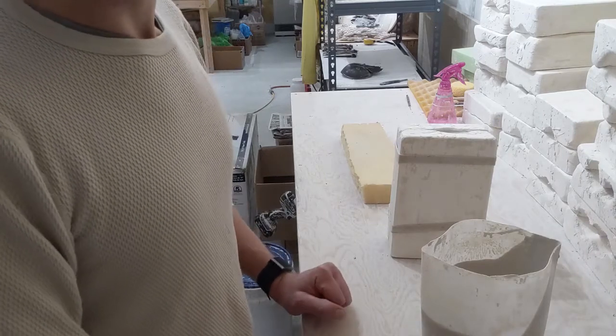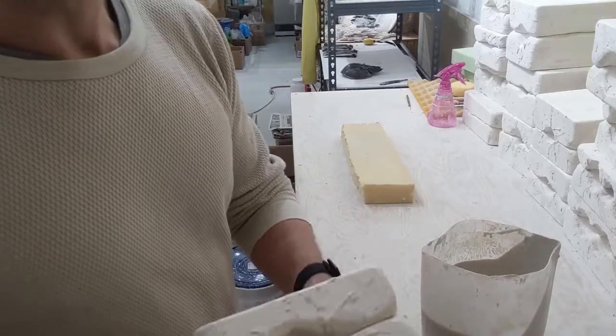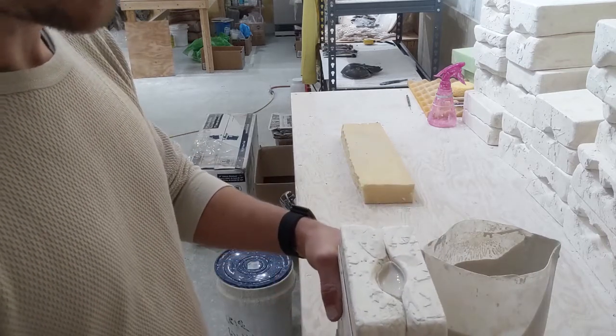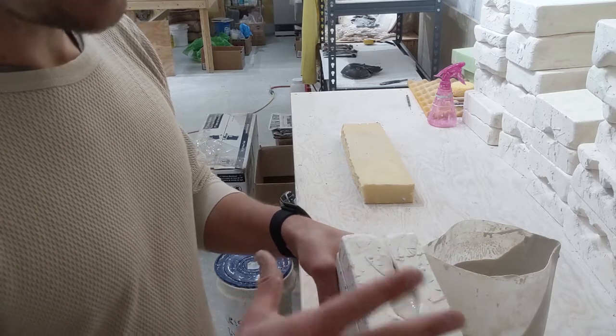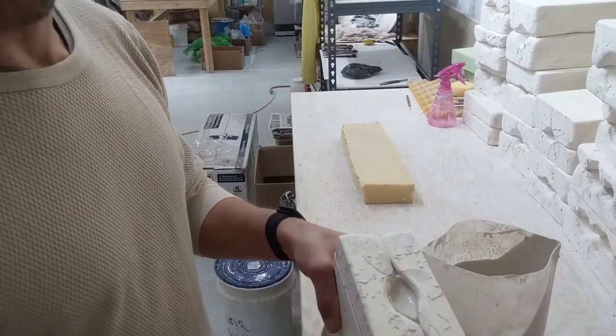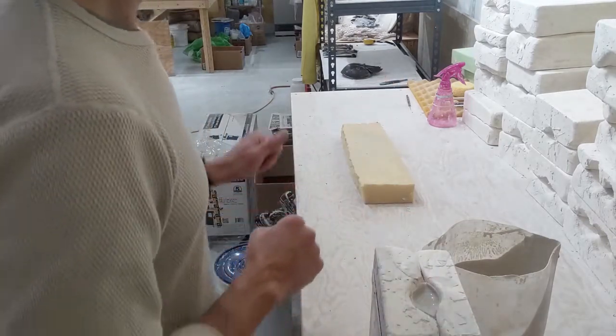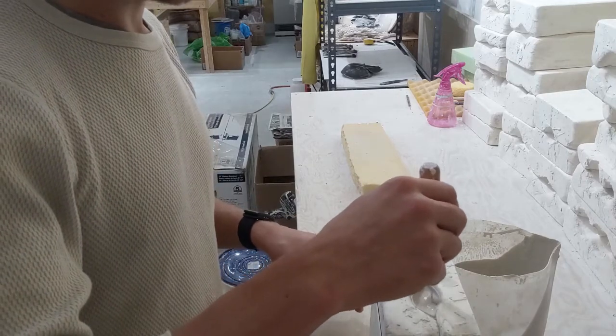Okay, so it's been not honestly not nearly 15 minutes, but since this is just a demo, I'm going to go fast. You can start to see the beginnings of the shell around the edges there, which is what we want. I did once or twice top this off while this video was paused — that would be very boring to watch. But slowly as the moisture from this slip is absorbed into the plaster, you'll start to see the level of slip in the mold go down. You just kind of want to keep that topped off throughout the process throughout those 15 minutes. But now we're just going to say that it's good enough.